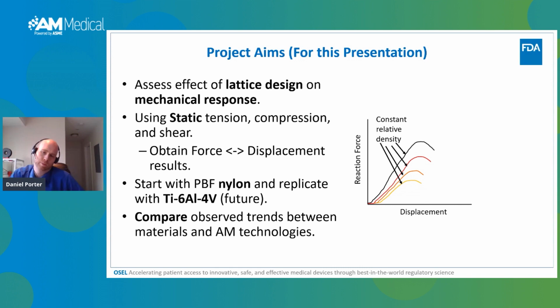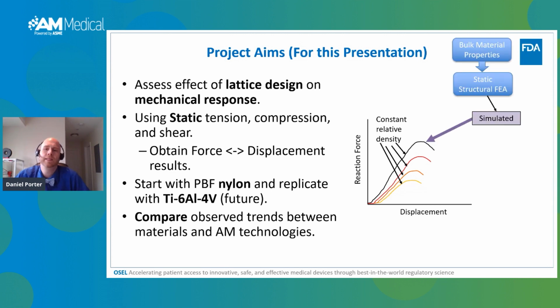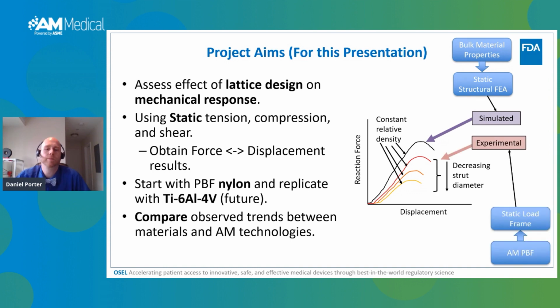Here's a graph of what we backed out with some preliminary experiments we did quite a while ago. What this is showing is reaction force versus displacement. Say you did an FEA on a bunch of different designs that had the same relative density, same cell type. So you took bulk material properties, you put them in an FEA, and you simulated a bunch of graphs. What we found is generally the simulations overlap. They all show the same performance. But if you actually took those designs, printed them out, and tested them on a load frame, what we found was that decreasing strut diameter actually gave degraded performance, and it was different from what we initially had simulated.